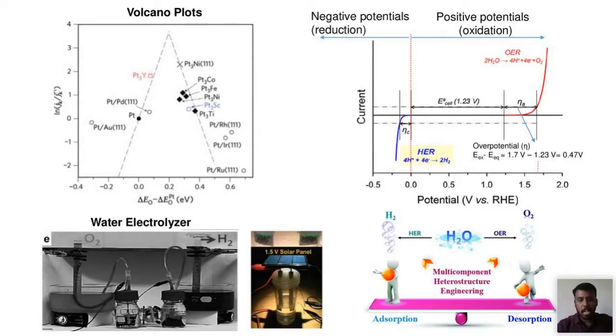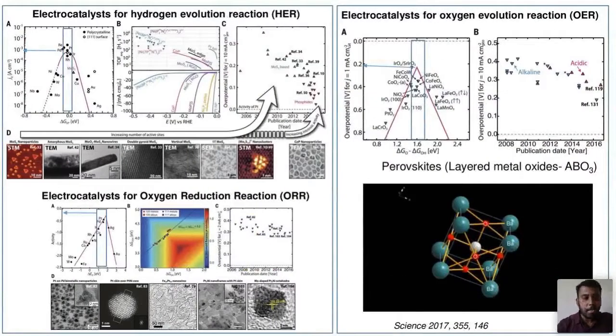This is a simple water electrolyzer with anode and cathode. Hydrogen evolution will happen at the cathode and oxygen evolution will happen at the anode, and you can collect the gases very easily. You can also integrate with the solar system like solar panel, and this is called PEC water splitting, photoelectrochemical water splitting. So multi-component heterostructure engineering, these are all different strategies. All these strategies are used to control the adsorption and desorption of the intermediate. So you have to get this information through DFT calculation, and you can design a system which has minimum adsorption energy, then you can have better activity.